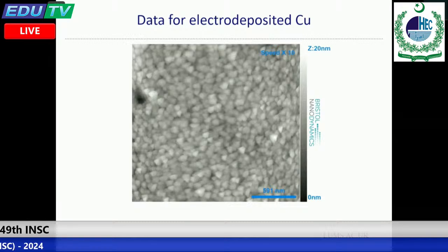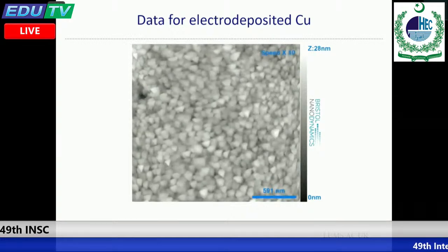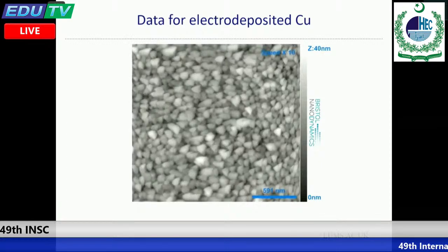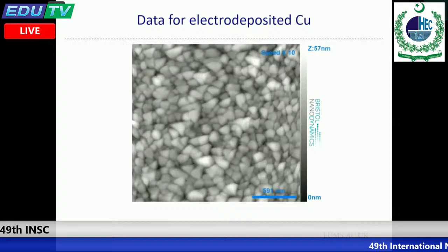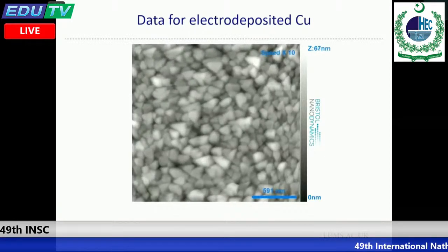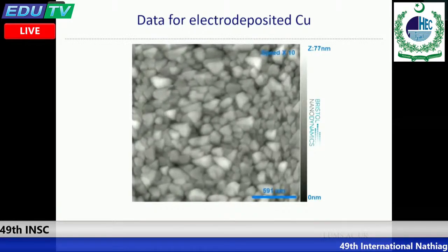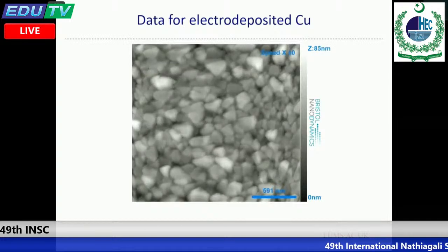So now let's have a look and see how this quite fine-grained structure becomes rough. This video is speeded up, but not by so much. The whole experiment only takes 1 or 2 minutes. So you can see it gradually getting coarser and coarser and coarser. So if you look at that, you see the surface coarsening taking place in real time. And that's actually the first time, as far as I know, that that has ever been seen. And for somebody who studies surface coarsening, to be able to see it as it happens is really rather nice.